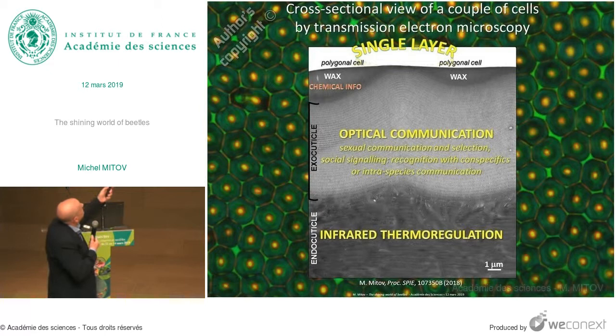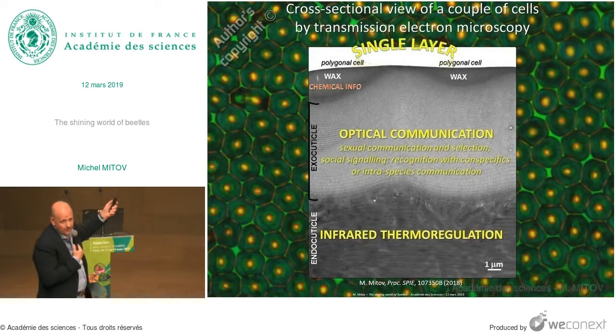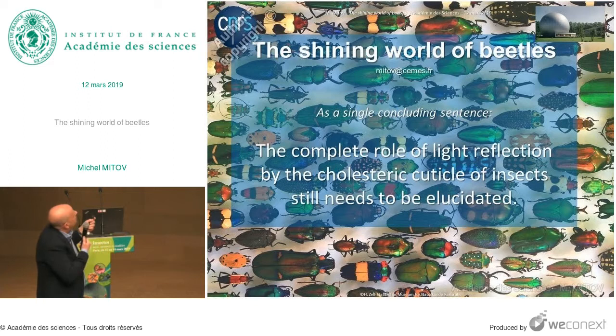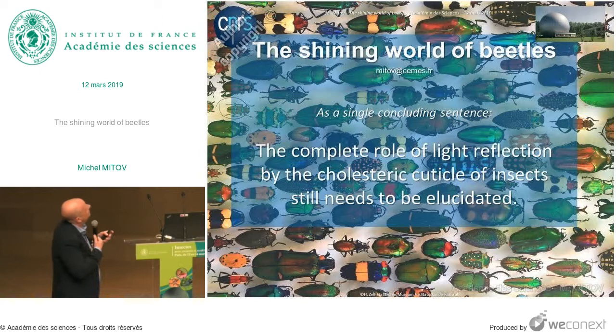If I add the second layer — the wax layer, which is in direct contact with the exterior — it acts as a barrier against desiccation and provides hydrophobic properties, but importantly pheromones are also present there, so we can speak of optical communication, thermoregulation, and chemical information. As a single concluding sentence: these carapaces are fascinating and very beautiful, but several hypotheses are available and the complete role of light reflection by the cholesteric liquid crystal cuticle of insects still needs to be elucidated. Thank you very much for your attention.